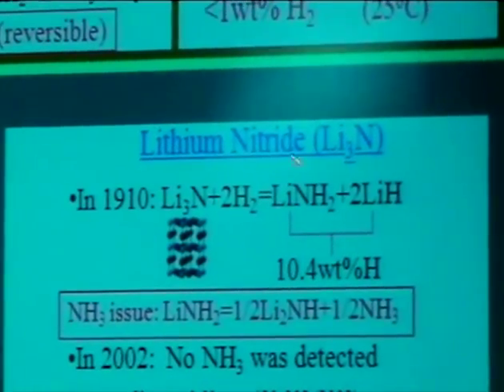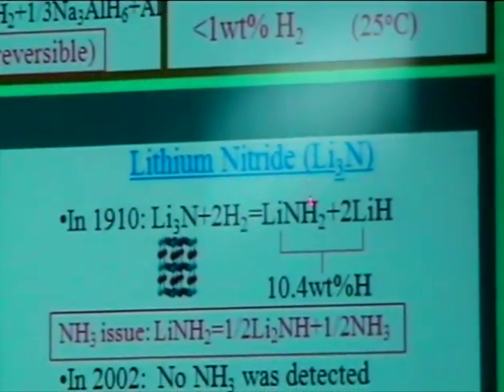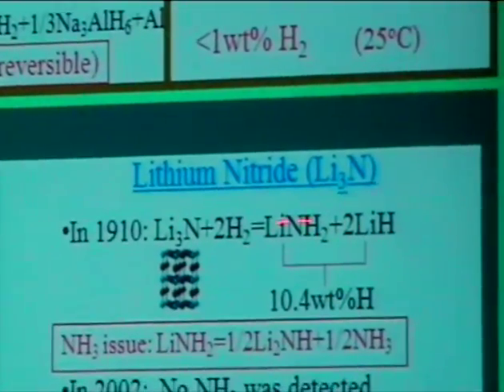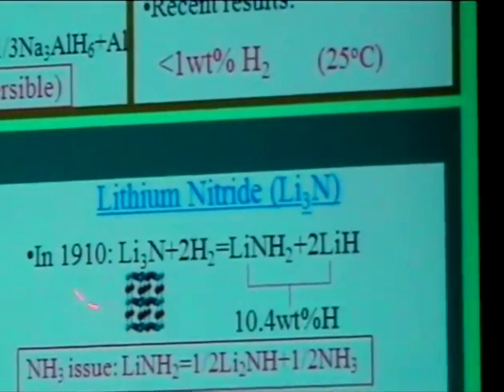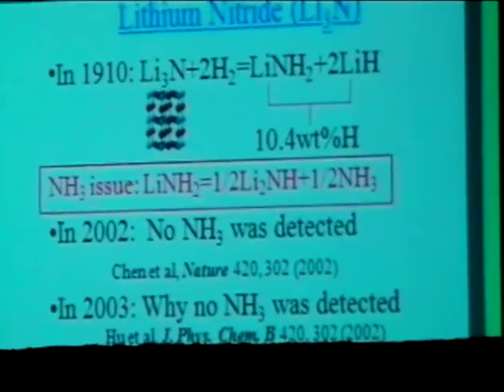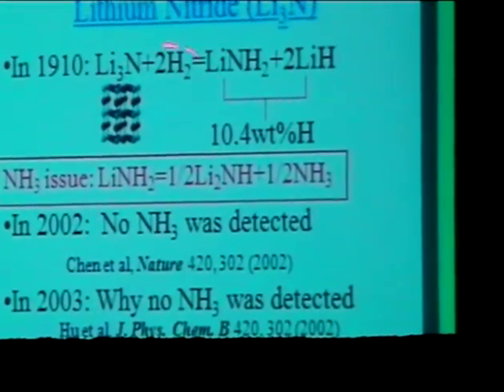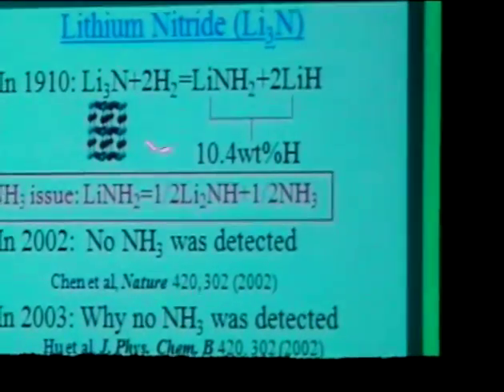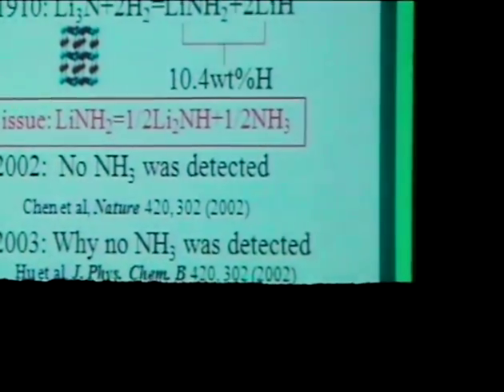Then another one, also in 2002, a research group reported lithium nitride. Lithium nitride can react with hydrogen to give lithium amide and lithium hydride. That one is not a new one. It was published in 1910 by a German scientist. But at that time, nobody paid attention to this reaction because hydrogen storage was not important then. The second reason is that lithium amide can easily decompose to ammonia, and this is the issue. Ammonia is a poison for fuel cells. So the two reasons: one is hydrogen storage was not important in 1910, and the second is the ammonia issue.